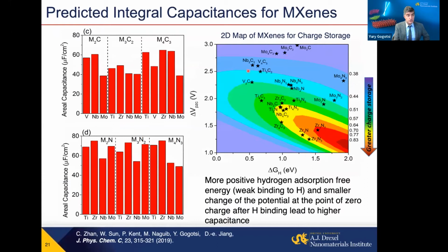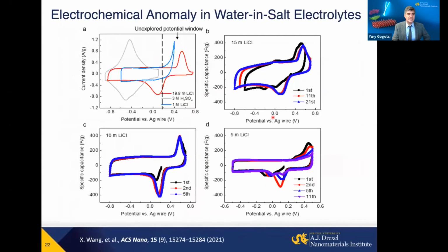Moreover, titanium carbide, which I showed you, is not the best energy storage material. Theoretically, many other MXenes have been predicted to produce significantly larger storage. But if you work with dilute aqueous electrolyte, if you work with, for example, sulfuric acid or other acidic electrolytes, we're always limited by voltage window. And voltage window determines largely also the amount of energy stored. So what we need is to expand the voltage window.